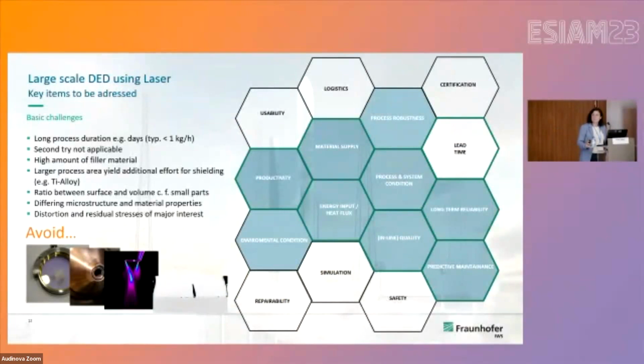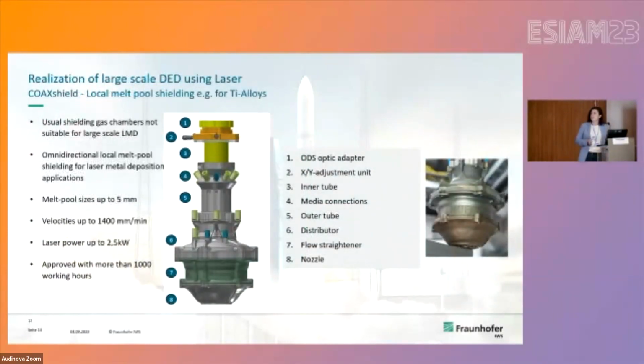And then obviously we need high productivity, in the range of kilograms per hour, of sufficient material. We studied the scope of working with wire and powder. Due to the geometrical complexity, we moved to powder approaches because the wire was not able to give us the exact geometry needed there. And obviously distortion and residual stresses are a huge issue. If we work for a couple of days and hours printing layer after layer for a 1.5 meter structure, you might have included residual stresses that lead to delamination, and even huge forces are related to the printing. So you also have to address safety in the lab and not have an issue with that.